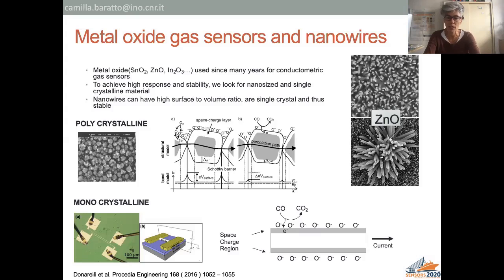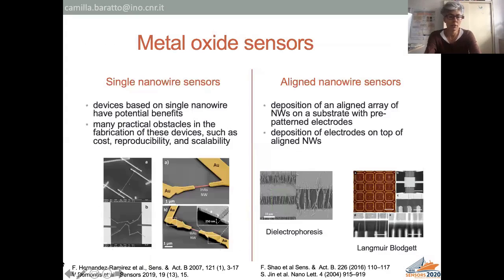nanowires, where a nanowire is a single crystalline device with a nanometer size diameter. And so you can have high surface to volume ratio along with an increased stability of the material. The best thing to do is to pick up one nanowire out of a mesh of nanowires and to put contacts over it. And in this case, the current is flowing through the axis of the nanowire.